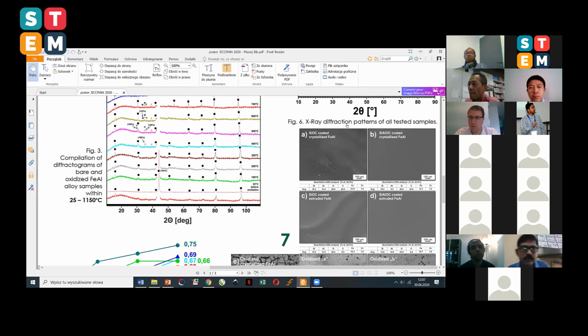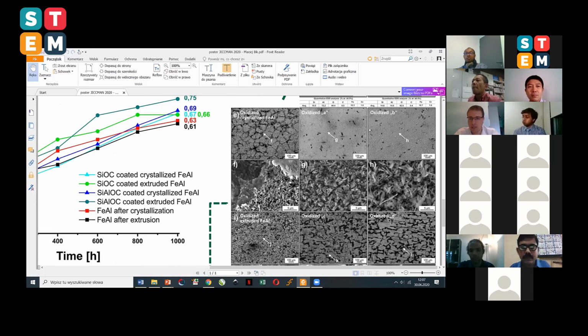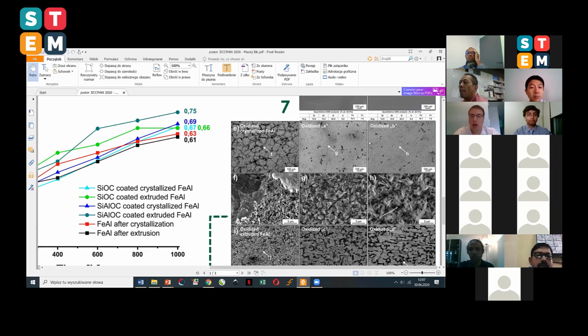And also then I would like to draw your attention to the microstructure studies. So first of all, images of coatings after their formation, and unfortunately it seems that the pure silicon oxycarbide material is inhomogeneous and cracked. However, in the case of aluminum-doped material, we could see non-cracked, fully tight, homogeneous coatings. And after oxidation, we see the full confirmation and the explanation of why we had such ambiguous mass change results.